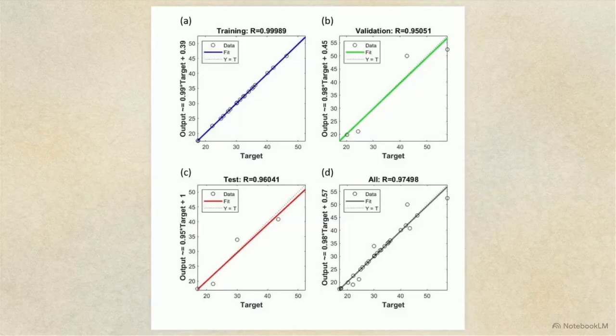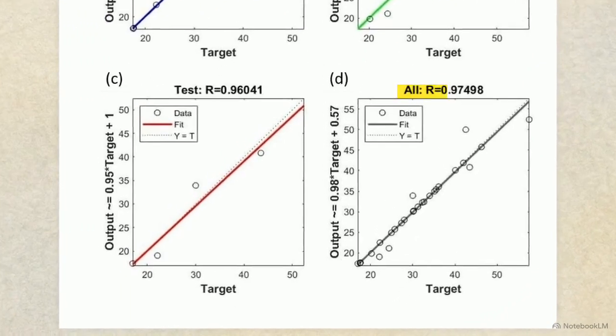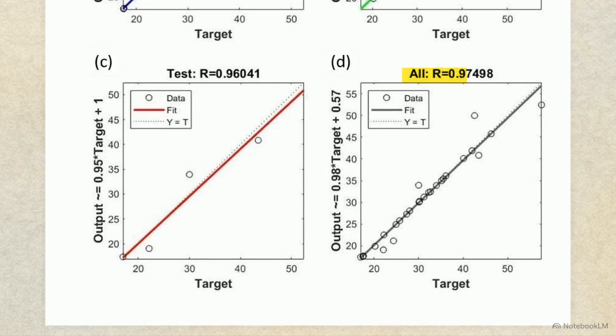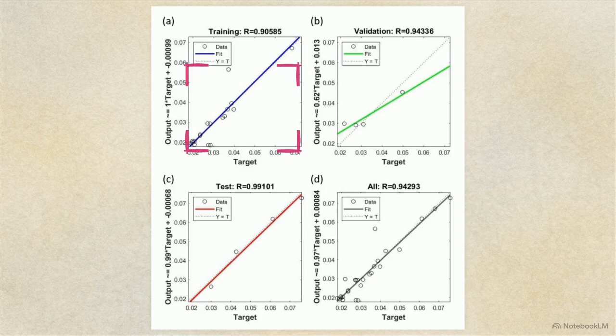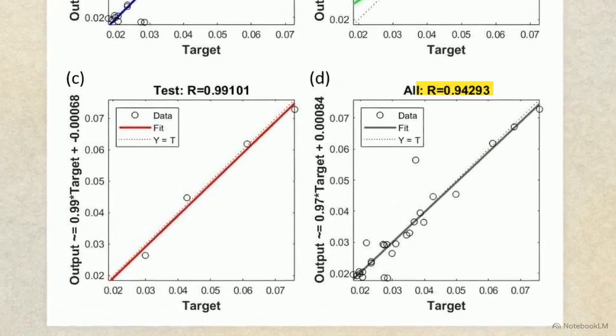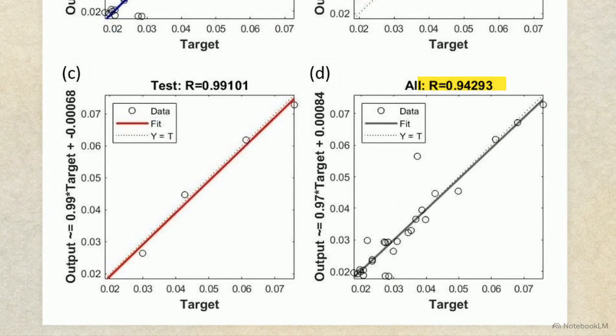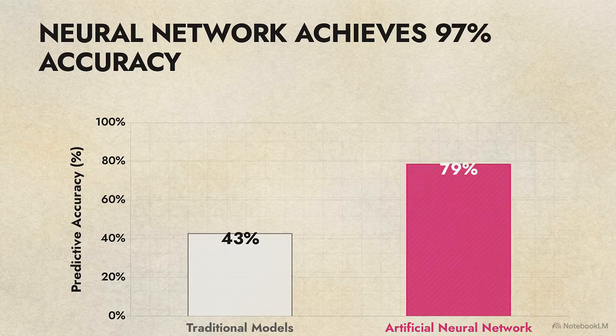These 4 regression plots visualize the network's predictive validity for tensile strength, mapping the model's predicted values directly against the actual physical test targets. The correlation is exceptionally tight, achieving an overall R value of 0.97498. A second network trained to evaluate a part's elongation at break yields similarly precise regression plots. The ductility model tracks with an overall R value of 0.94293. Traditional mathematical models failed to predict polymer behavior up to 57% of the time. The neural network predicts structural outcomes with 94 to 97% accuracy.